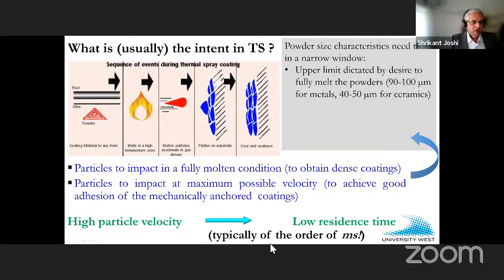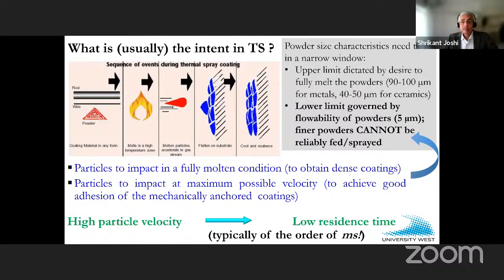Now, if you look at the spray grade powders that are out there, typically there's an upper size limit, which is dictated by what you can melt during this short residence time. So for relatively lower melting metallic powders, it could be slightly high. The upper limit could be 90 or 100 microns. For ceramics, it's lower. And then, of course, depending upon what process you use, it could change a little bit. But this is the reason for having an upper limit on your powder feedstock, which is easy to appreciate.